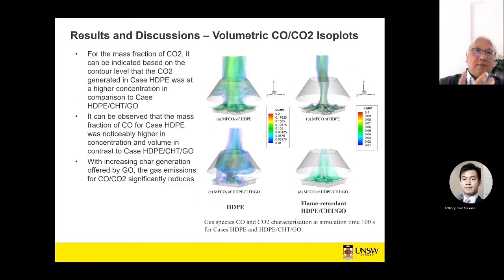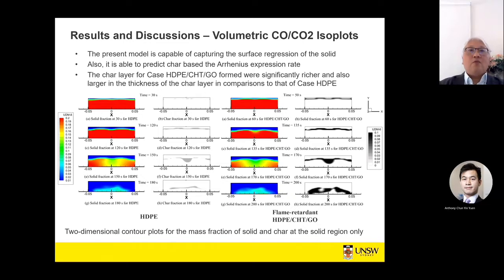The good thing about the CFD model now, since we compare with the concurrent experiment, is that we could extract useful information on the carbon monoxide and carbon dioxide emission during the degradation process itself. As you can see here, with a flame retardant HDPE, the quantity of CO2 is much less. Also, what our CFD model could do is look at the surface regression of the polymer as it undergoes degradation. That means we can even track the melting of the material itself. As you can see here, the comparison is being predicted.